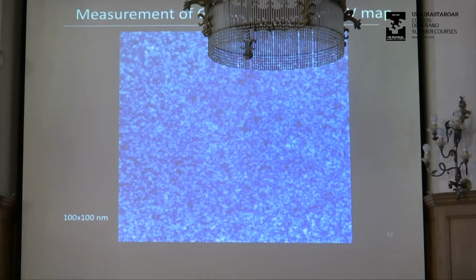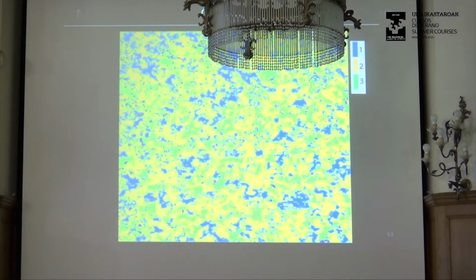Of course, it's extremely inhomogeneous, but we have a huge advantage because we have statistics on the gaps. In this field of view, we could take 200 times 200 points and measure the gap at every point. So we have huge statistics, and I can show you what that looks like. This is what is called a gap map. This is not a conventional gap map. All I've plotted here are regions of 1 gap, 2 gaps, and 3 gaps.